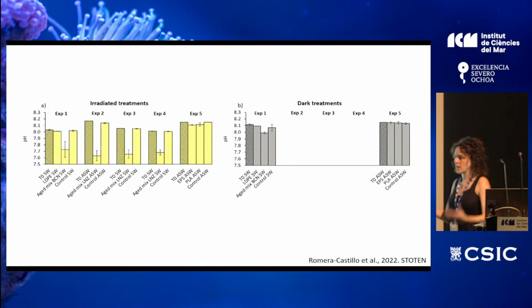So we did several experiments, only the abiotic part that I showed you at the beginning, this kind of experiment, just to see if the pH was decreasing after the irradiation of the sample during the generation of the leachates. So the stippled bars are the time zero of the experiment, and the last bar in every experiment is the control without plastic. And then we have also some new plastic like this LDPE here, and this EPS and PLA biodegradable here. But we also have a different type of aged mixed plastic here. And you can see that in all the treatments with the aged plastic, the pH decreased in all of them. While in the new plastic, the decrease was very slight or sometimes not significant.